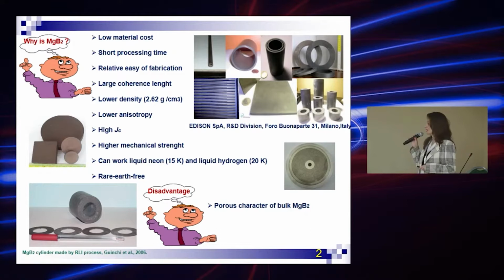As known, magnesium is a type of common metal, so we expect low material cost, short processing time, and relatively easy fabrication. Today, bulk MgB2 can be prepared by spark plasma sintering in less than 2 hours. And its BCS features: MgB2 coherence length is quite high compared to other high temperature superconductors, and maybe the most important feature is the lightweight, due to lower density and lower anisotropy and high JC.